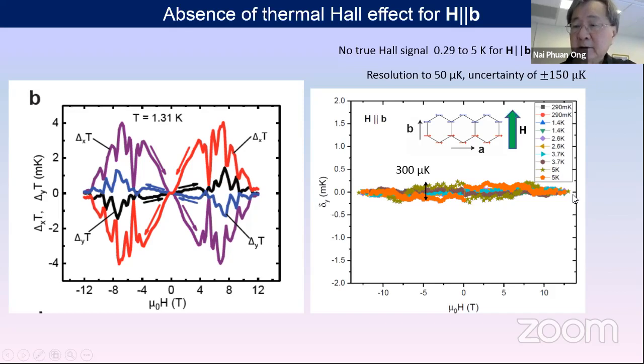Using ruthenium oxide thermometers, we can actually resolve at 1 Kelvin changes of 50 microkelvin. Remember, the sample is sitting at 1 Kelvin. The temperature gradient across it is perhaps 100 millikelvin. We can resolve the transverse gradient to 50 microkelvin, thanks to the heroic efforts of Tong and Peter in the last couple of years. But that's not the end of the story, because there are uncertainties that cause these ups and downs. The 50 microkelvin is the width of the curve, and the uncertainties are plus and minus 150 microkelvin. Anyway, this gives an idea of how we can now push the measurements to very high resolution.